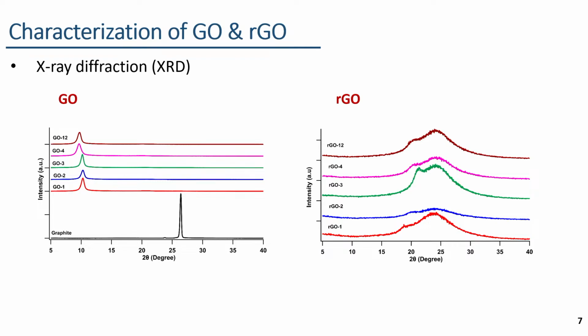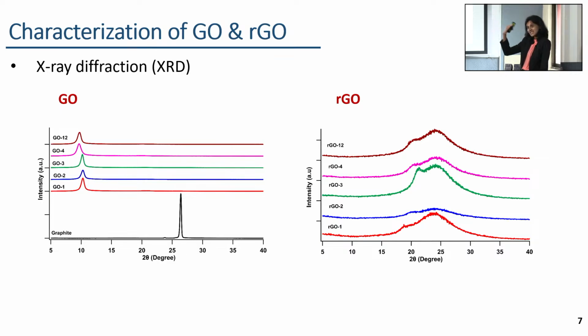I know very little about this field. So this is RGO1, RGO2, RGO3, 4, and then all of a sudden 12. Why did you select those? After RGO4, is there a particular reason to go to RGO12? No, sir. Normally the improved Hummers method is carried out for a 12-hour synthesis. So we wanted to go to oxidation times less than 12 hours, and that's why we selected 1 to 4 hour synthesis. When we compare these results, GO4 and GO12 have similar properties, so there is no need to go beyond GO4. Thank you.